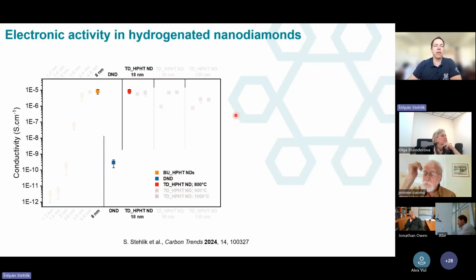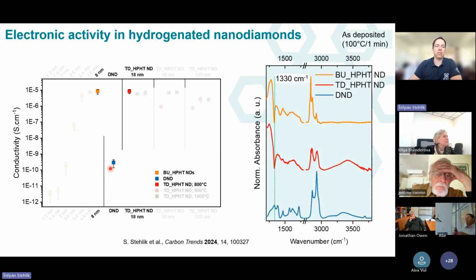What else we compared was the electronic activity, especially the conductivity. So we showed that both HPHT nanodiamonds, this bottom-up and top-down, were quite conductive compared to the DNDs, which were non-conductive, or at least 5 orders of magnitude lower conductivity. So it's also correlating with their negative electron affinity and the positive electron affinity, but also maybe there is some influence of the structure and nitrogen whatsoever. This we don't know yet.